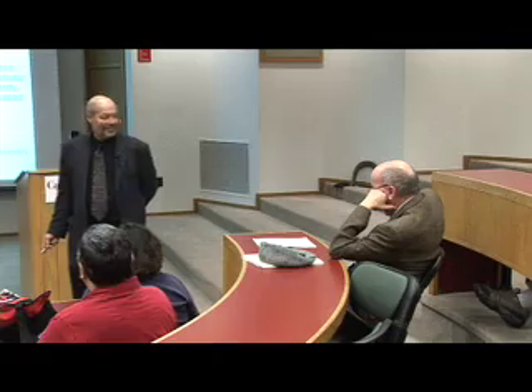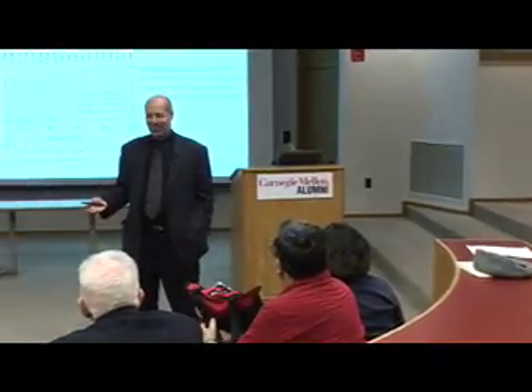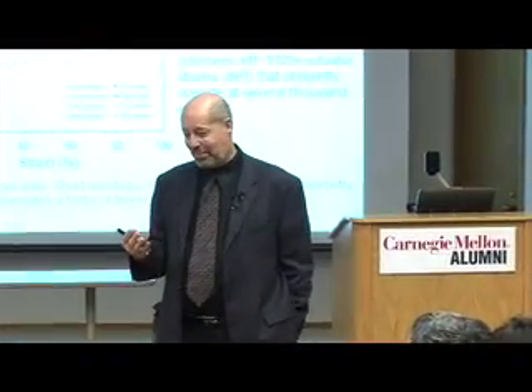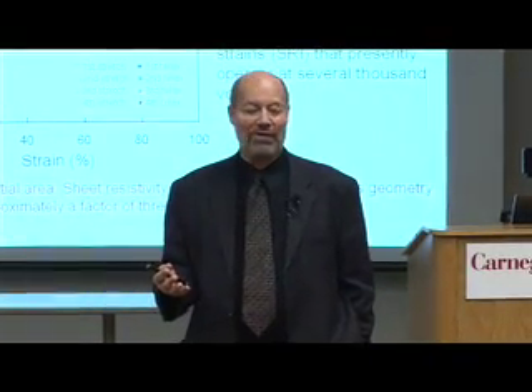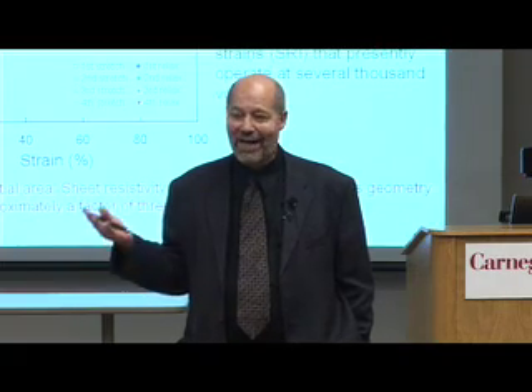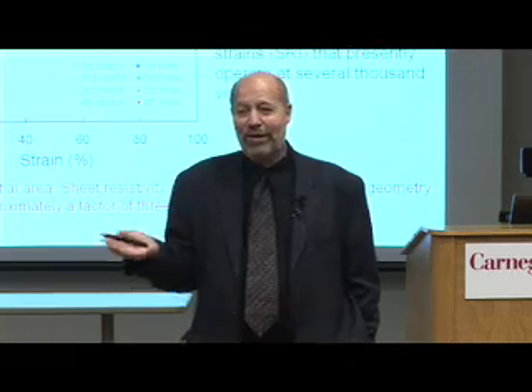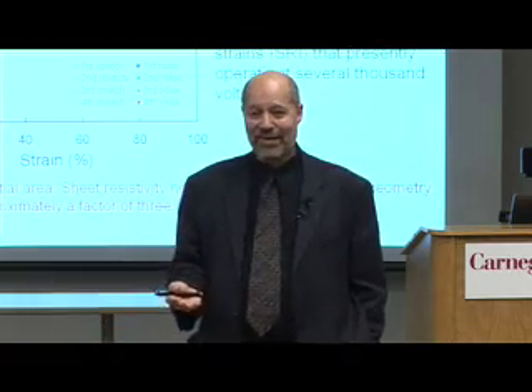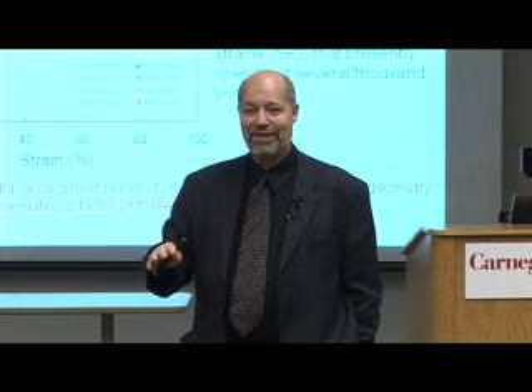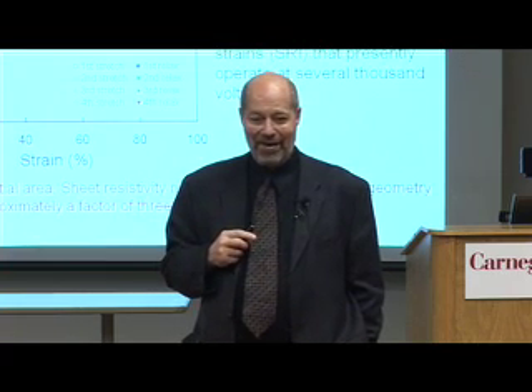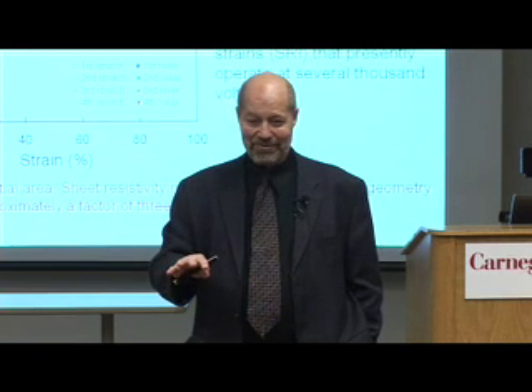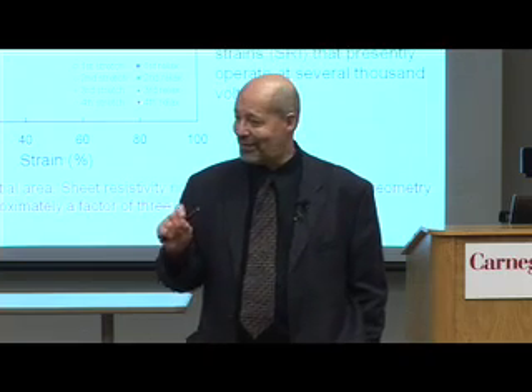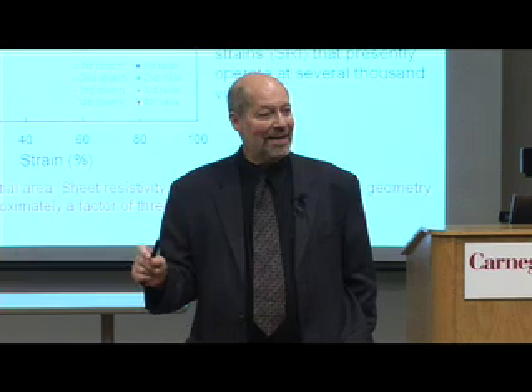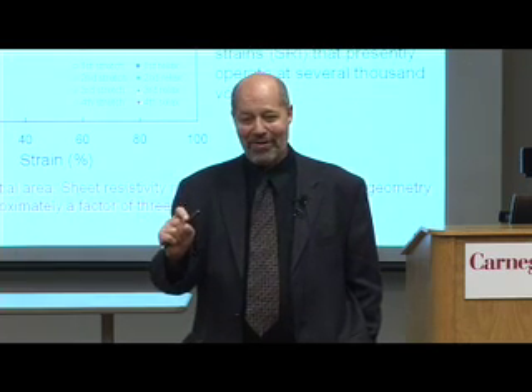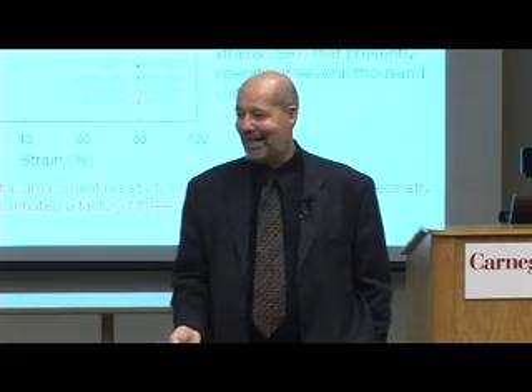What happens to the electrical properties when you stretch it? Yeah, that's what I said. The conductivity doesn't change. And this is very important. People want high-stroke artificial muscles. And artificial muscles is an area in which I do a lot of work. The problem is people can get an artificial muscle stroke of 300%. But what electrode material can deform 300% or even 100% or even 30% without changing its electrical conductivity? So what people do, if they use an artificial muscle material such as silicone rubber, they put greases that are loaded with conducting particles on top of the sheets as electrodes. Now the thickness of the grease has to be a certain amount or you can't use an electrode. So unless you use thick silicone rubber, your whole actuator stack, your artificial muscle stack will be all grease.